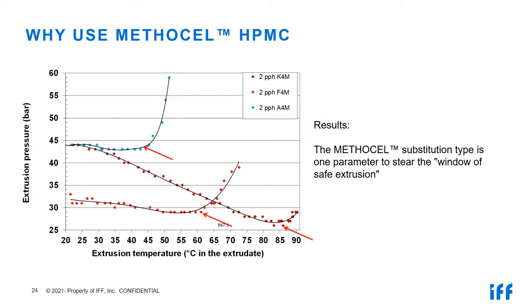Yes, 3 other examples now. We are comparing 3 times the same concentration of 3 different cellulose ethers. Here in this graph, we are talking not in percent, but in pph. Sorry, but maybe you are doing the same. pph means parts per 100 weight, and this is a slightly different calculation. So we are calculating parts of cellulose ethers on top of 100 parts of ceramic dry ingredients, and of course then you have still to add the water.